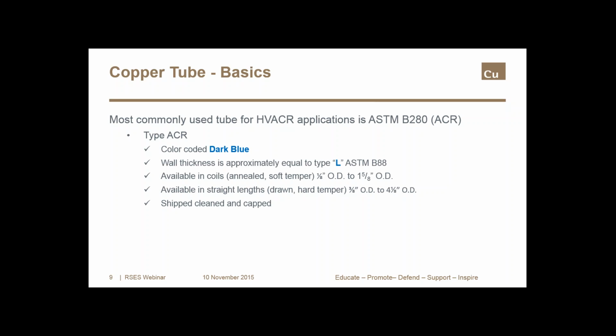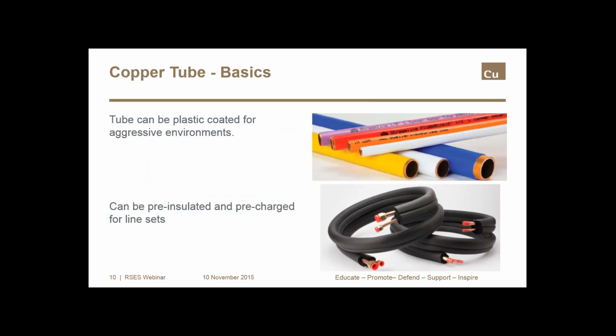For air conditioning and refrigeration, type ACR tube is most common. It meets ASTM specification B280. It is color-coded blue and has a wall thickness that's most like type L B88 tube. Coiled or annealed tube is available in diameters from 3/8 of an inch up to 1 5/8 inches OD. In straight lengths, drawn tube or hard temper is available in diameters from 3/8 all the way to 4 1/8 inches OD. Copper tube can be plastic coated for what we call aggressive or corrosive environments. The tube can also be insulated or even pre-charged.